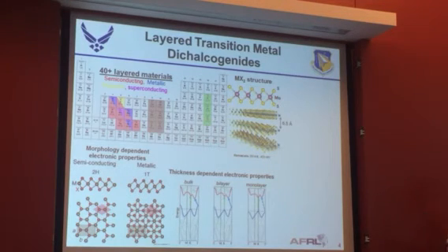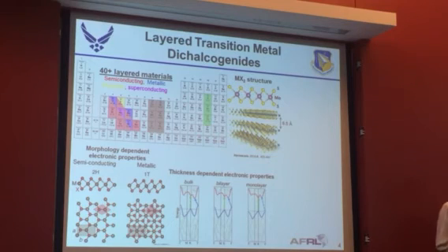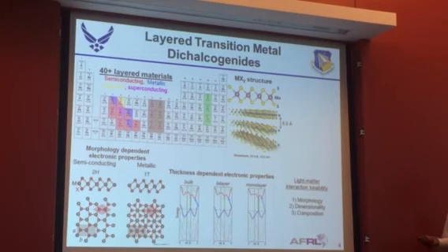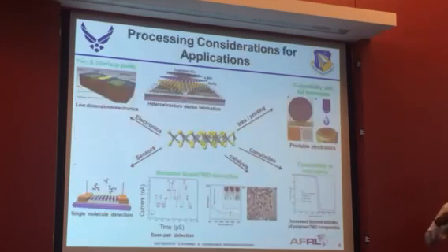As a key point, you can tune the thickness of these materials. You can get a transformation of electronic and thermal properties as you reduce the layer thickness from bulk crystallites to bilayers to monolayers. Many emergent properties occur at the monolayer limit, which is why vapor phase techniques are so widely used — they can easily target monolayer species. Because of all this, you get a large window of opportunity for tuning the light-matter interaction through morphology, dimensionality, and composition of these materials.